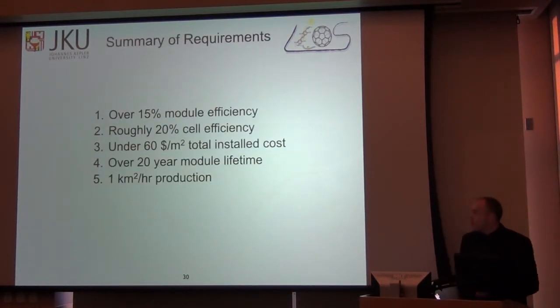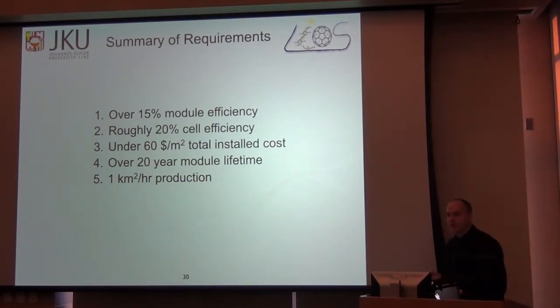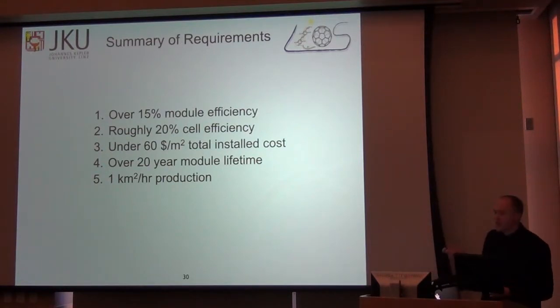So for photovoltaics, for large-scale power generation, we have pretty lofty targets. So we definitely need 15% module efficiency, and in order to get that, we need roughly 20% cell efficiency. So in the long term, the theoretical maximum of about 15 or 16% cell efficiency for this heterojunction organic solar cell structure is insufficient for many reasons. Our cost targets, though, under $60 per meter squared installed cost, organics are one of the more promising technologies.